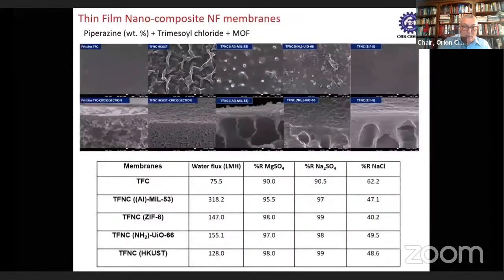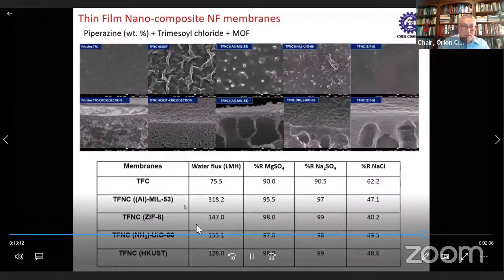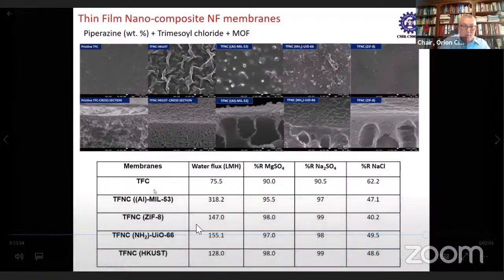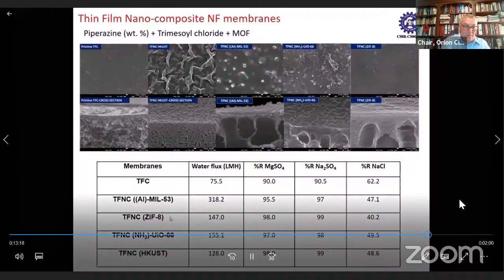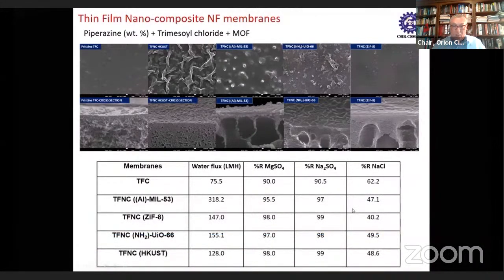These metal organic frameworks were used to prepare thin film nanocomposite nanofiltration membranes utilizing piperazine, trimesoyl chloride, and metal organic frameworks synthesized using microemulsion droplets. We formulated different nanofiltration membranes which were tested for the separation of a mixture of salts. So we took a mixture of magnesium sulfate, sodium sulfate, and sodium chloride, and using the prepared thin film nanocomposite membranes, we can see that all the salts were easily separated using these membranes.